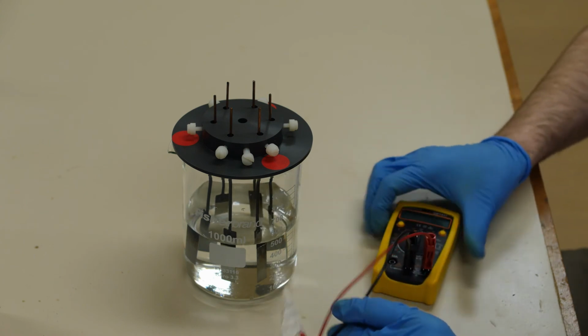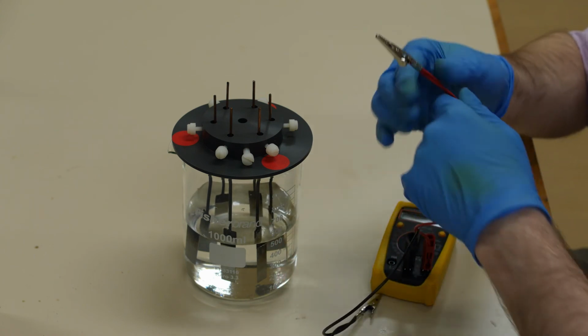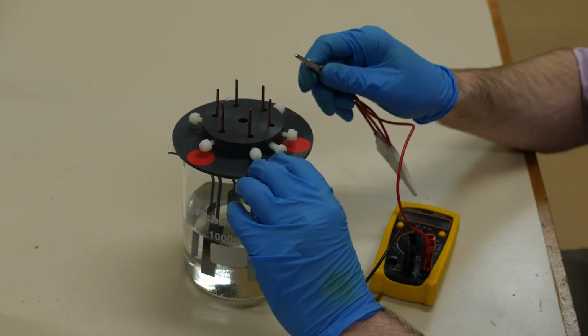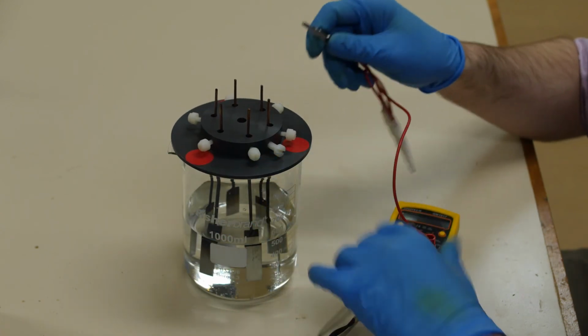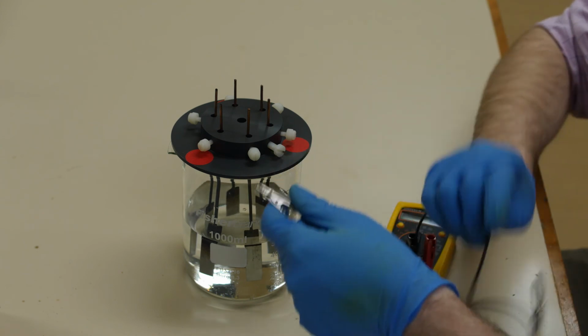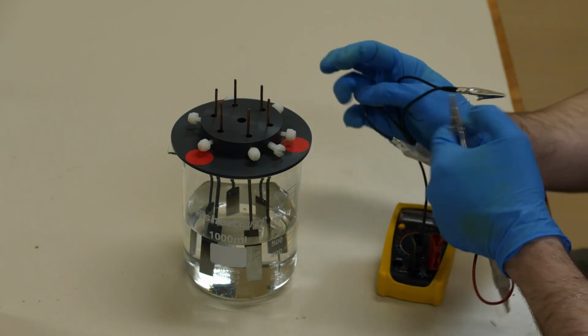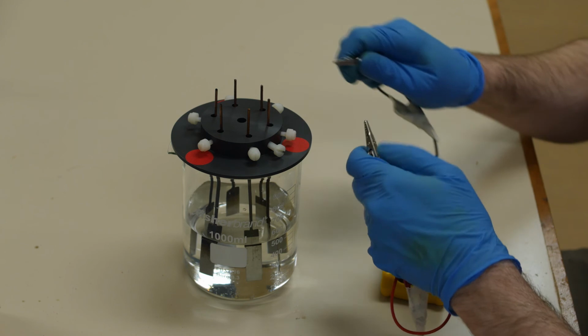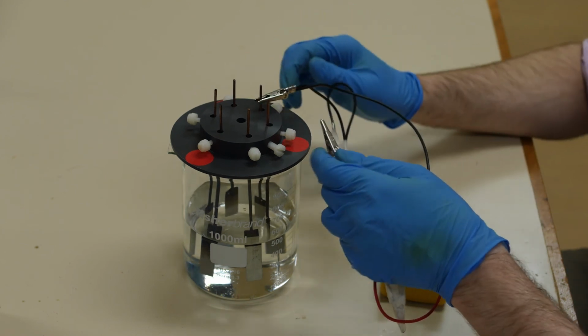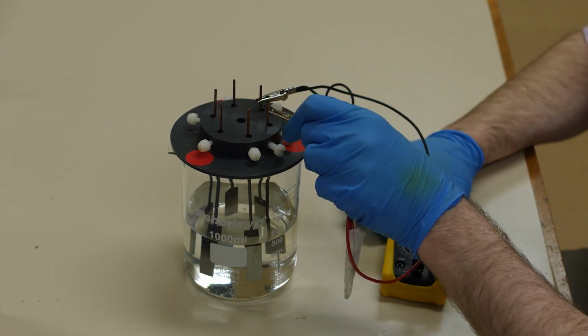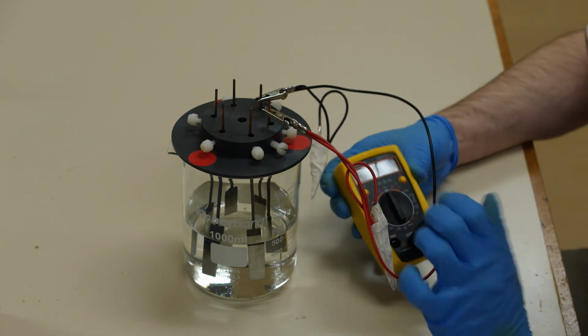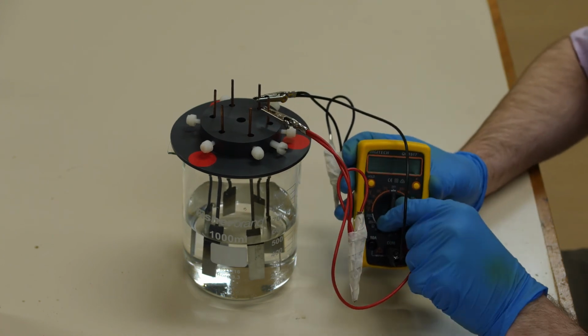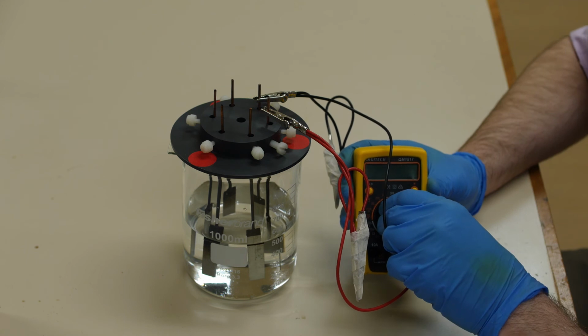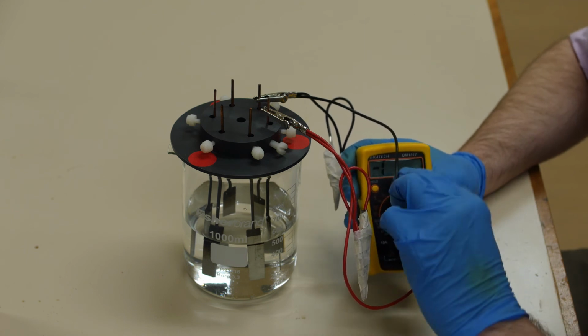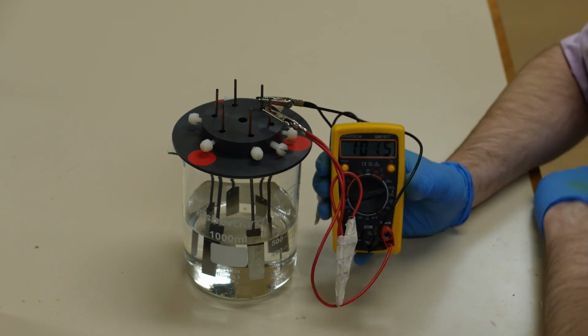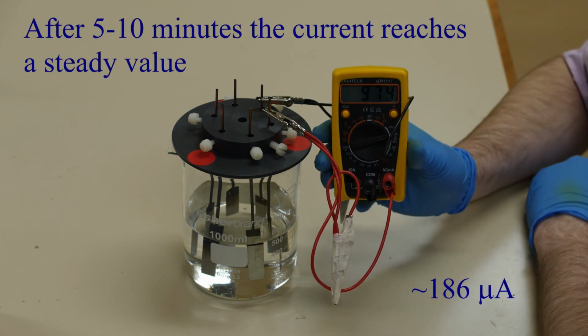The current voltage of each galvanic couple can be read using a multimeter. Part of the circuit in a galvanic cell carries charge via the migration of ions in solution. It takes about 5 to 10 minutes for the diffusion of ions in the electrolyte solution to reach a steady rate, and during this time current and voltage will continue to change.